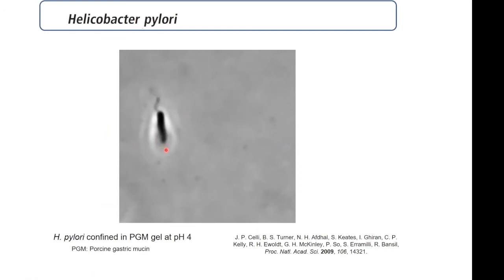But the amazing thing is, if you look at one Helicobacter pylori, which we know can go through mucus, if you look at one single one, it doesn't seem to be doing so great. It seems to be spinning, but it's actually not swimming. So it's small enough to make it through the network, but somehow it's still stuck. So it isn't quite so trivial. But we do know they're able to go through mucus because, after all, otherwise they couldn't cause the stomach ulcer.